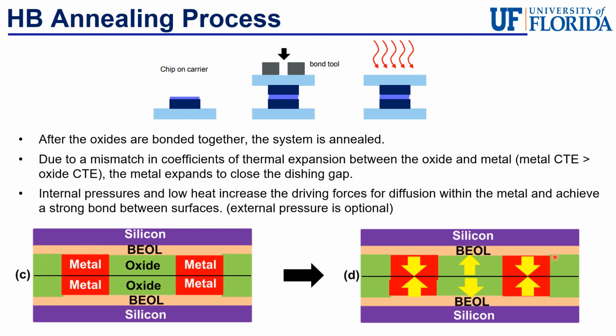Here in step D, as the metal continues to expand after filling the dishing gap, the internal pressure and the sustained heat will effectively increase the driving forces for diffusion and allow the crystal structure of each metal to form a strong bond with one another, and it will also allow the crystal structure to relax, reducing the defects and grain boundaries that could scatter any conductive electrons that are trying to move through it. Effectively, the interface between the metal pads is annihilated, and the two metal components come together to form a single